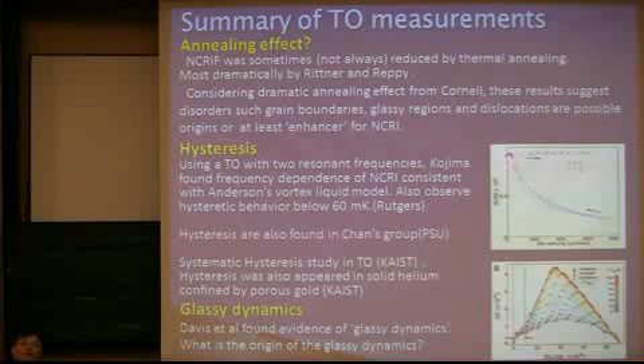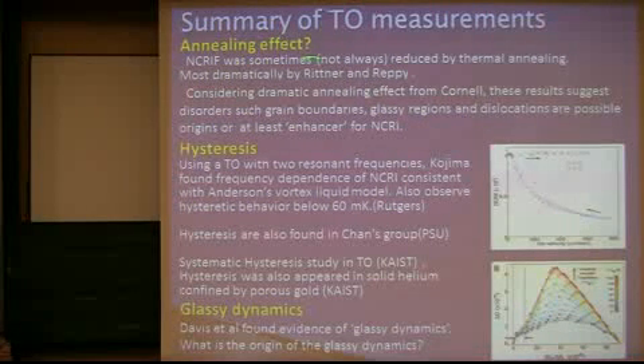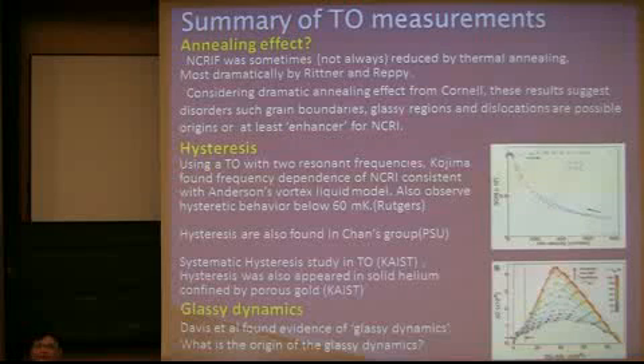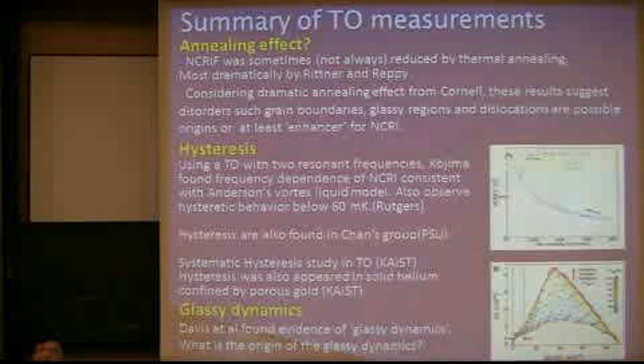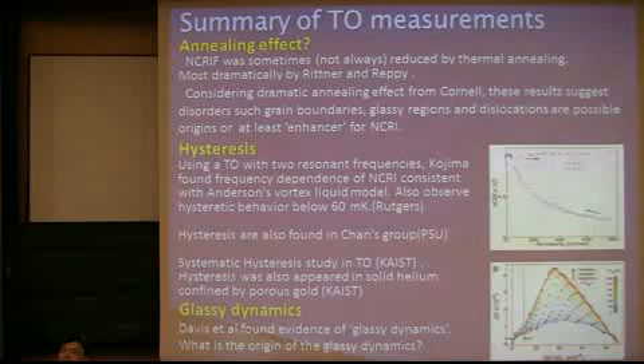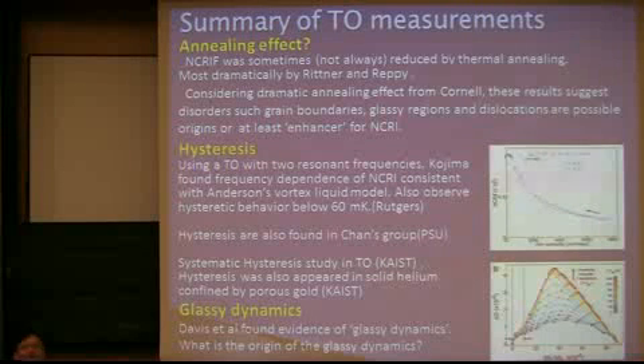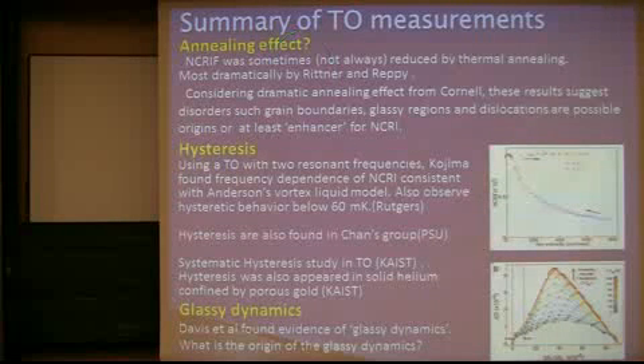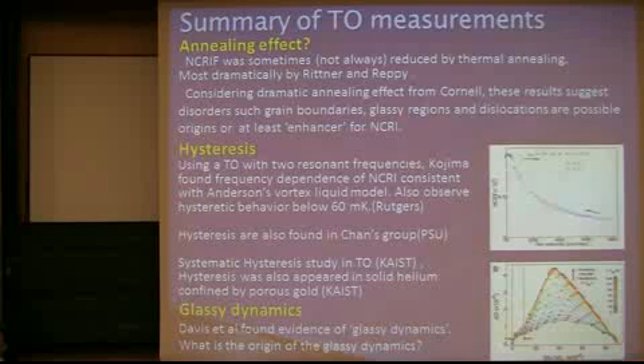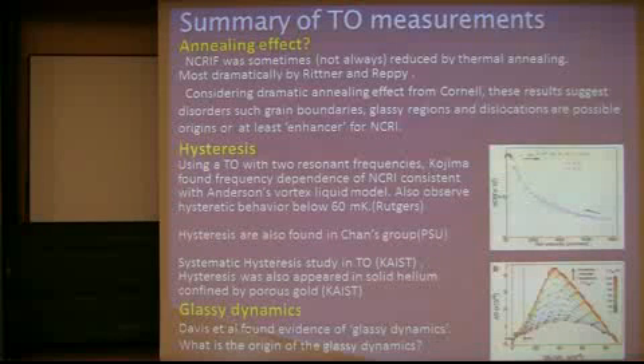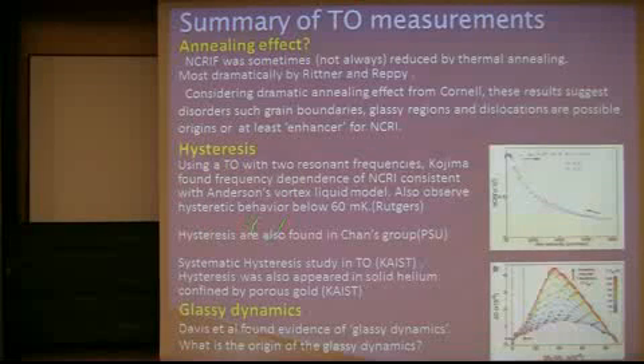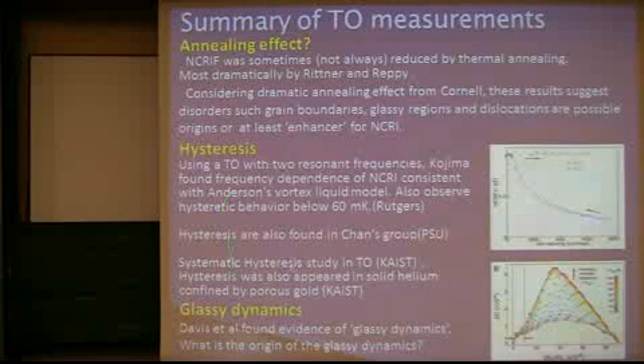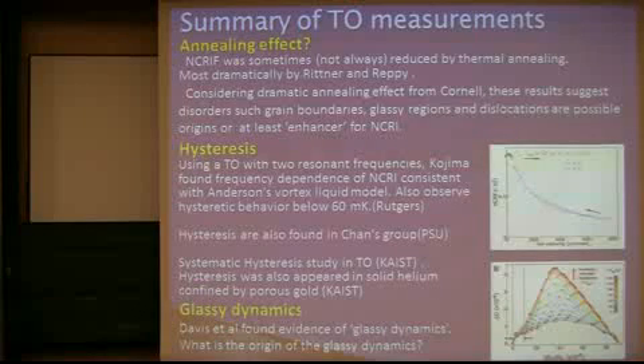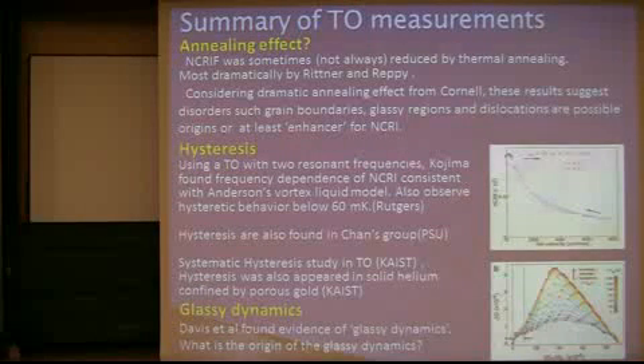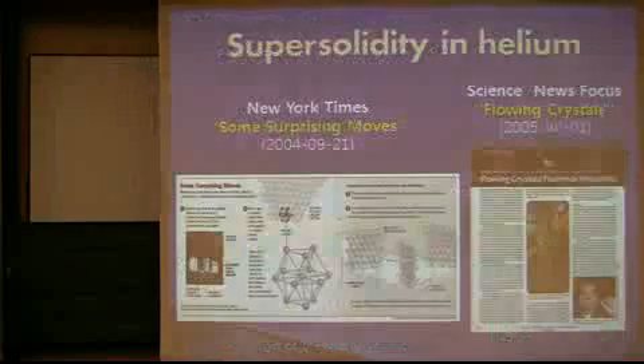Unfortunately, or probably fortunately, there are other experimental results which are very difficult to understand with just the conventional superfluid scenario. There is an annealing effect. When you anneal the solid sample, the total signal is strongly dependent on this annealing process, and hysteresis also appears in this measurement, and some people report glassy dynamics. I'm not going to go into the details of this experiment.